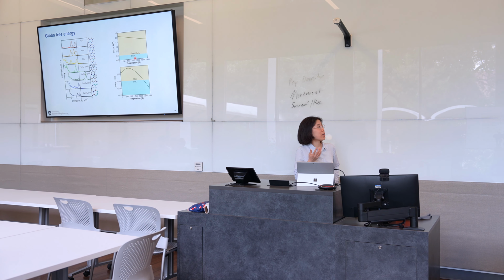In other words, at this synthesis temperature, DAP is not stable. So that means DAP should be excluded from our list. Our candidates left now are CBC and CNC, the trimers. If we look at CBC and CNC, you can see their Gibbs free energy difference is actually very small. So that means most likely both of them coexist in our sample.